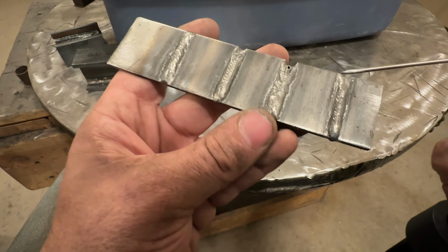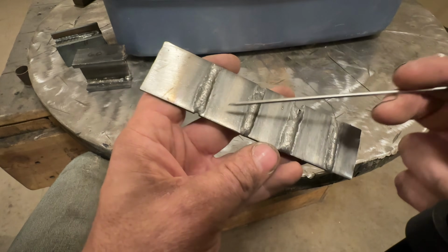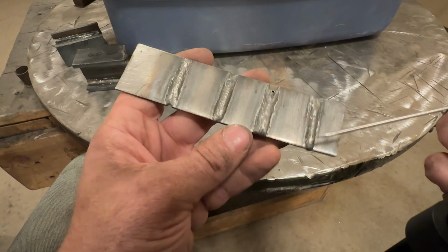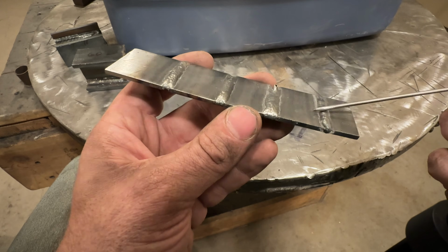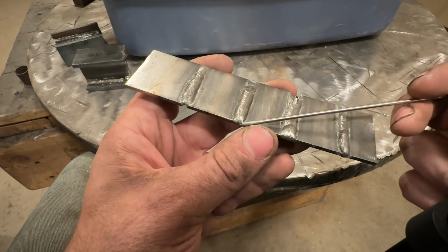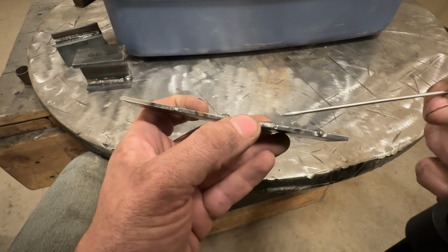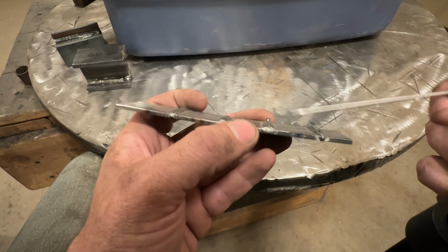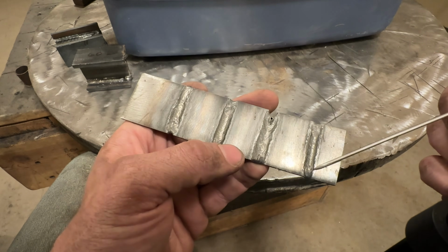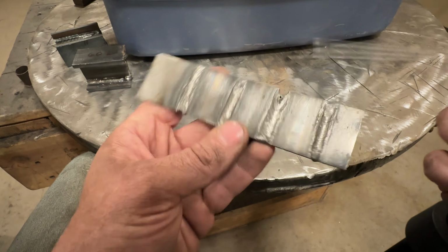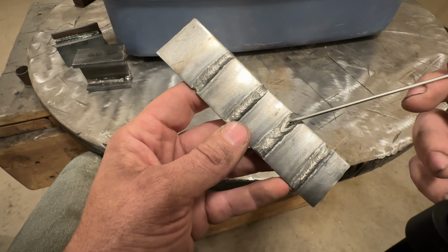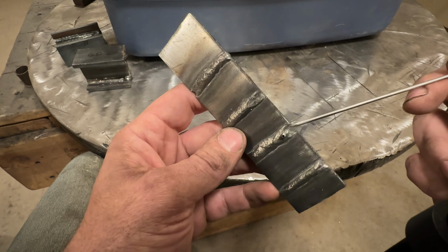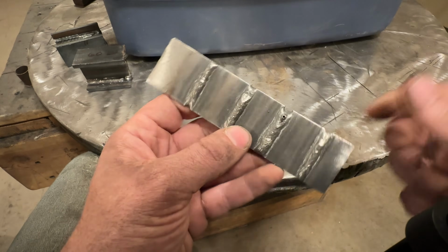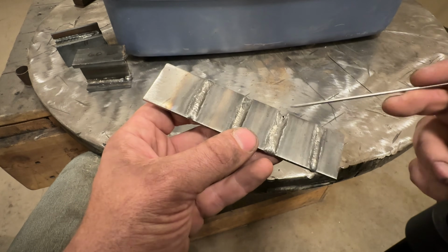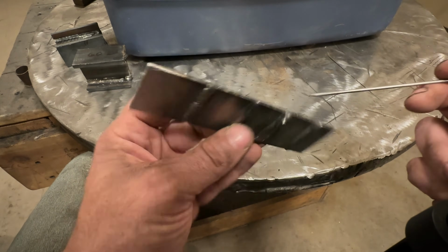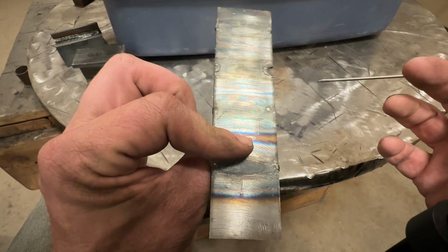This is a little bit colder. Use shadows to your benefit. You see how you tip this down and you start seeing a lot of shadows? It's kind of telling you that the weld is humped up like this, and you're seeing a shadow at the toes because it just didn't wet out that well. We got porosity here, a gas bubble that failed to escape, and we blew off the end. So here, settings are more of an issue. They're not in line, or travel speed isn't.